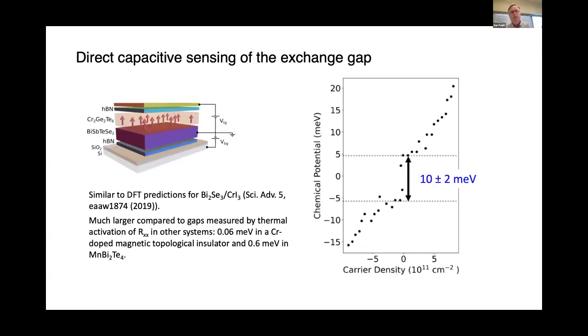insulators. We can get a better value of the exchange gap through direct capacitive measurements. So using the techniques that Emanuel Tutuc first pioneered for looking at bilayer graphene, and the MIT group applied previously to topological insulators too. Essentially, with both top and bottom gates, you can use the bottom surface of the topological insulator that's not gapped as a sensor to detect what happens to the chemical potential in the top surface as you tune the top gate voltage. With that technique and a little bit of algebra, you can map out directly the chemical potential on the top surface as a function of the carrier density. And at the Dirac point, we see a jump of about 10 plus or minus 2 millielectron volts. So quite consistent with the high temperature scale we expect from the previous measurements due to this exchange gap.